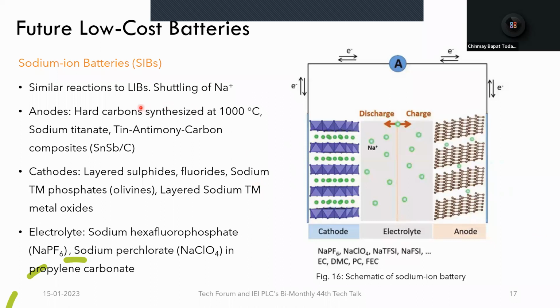Sodium-ion batteries work with reactions similar to lithium-ion batteries, the only difference being that sodium ions shuttle between the two electrodes. For anodes, we have hard carbons, that is disordered carbons, which are the opposite of ordered graphite carbons, or sodium titanate, tin antimony composites as the anode. For the cathode, we have similar structures as we saw before in the form of layered sulfides, fluorides, sodium transition metal phosphates, or sodium transition metal oxides. Electrolyte choices are sodium hexafluorophosphate or sodium perchlorate dissolved in a suitable solvent such as propylene carbonate.